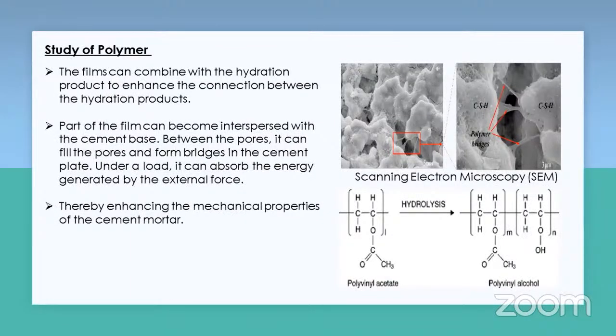Studying of polymer. Here we decided to additionally apply polyvinyl acetate to generate extra bond between cement particle and fine aggregate. The structure of cement mortar had to positively change because of the additional polymer components. However, PVA hydrolysis occurs when it reacts chemically with calcium hydroxide, which is produced of Portland cement hydration. The following process is the crystallization of calcium acetate. Calcium acetate crystal dimension is extremely unstable because of its hygroscopic characteristic.